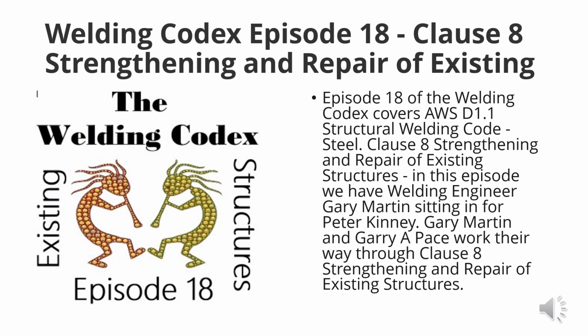So member discontinuities, 8.5.2, when required by the engineer, unacceptable discontinuities in the member being repaired or strengthened shall be corrected prior to heat straightening, heat curving, or welding. Before you start bending things, you probably want to fix the unacceptable discontinuities, but it gets back to when required by the engineer. Yeah, so if you've got a structure that has suffered some deformation or damage due to a weld failure and you're restoring it, you're likely to have some cracks, fissures, delaminations that you're going to have to take care of before you complete your weld repair.